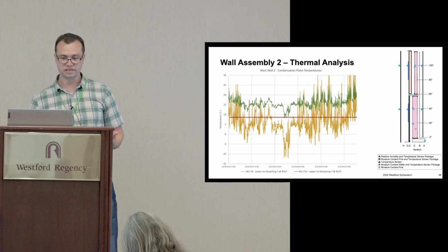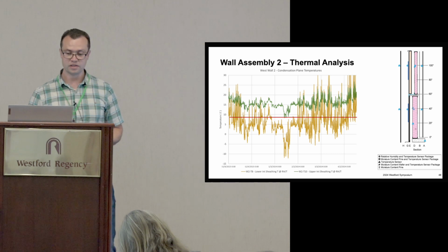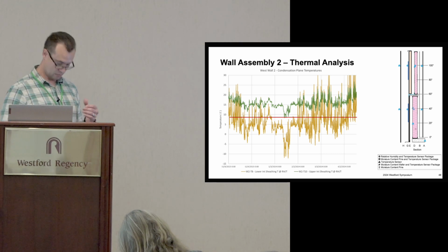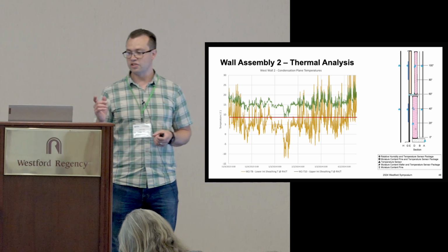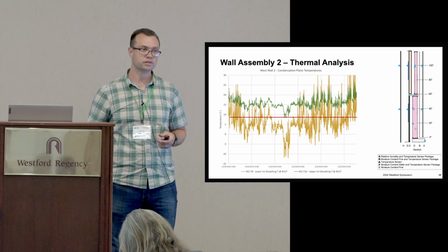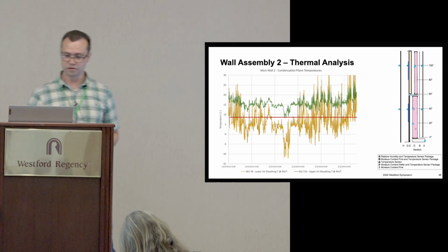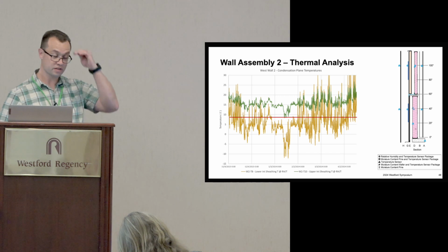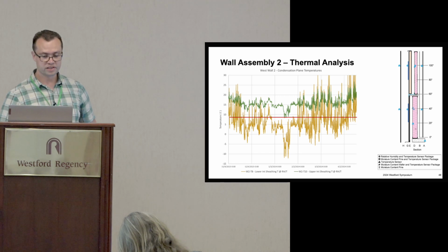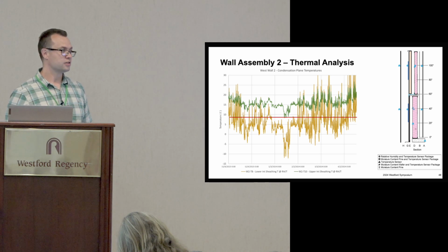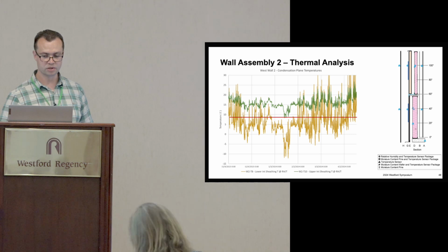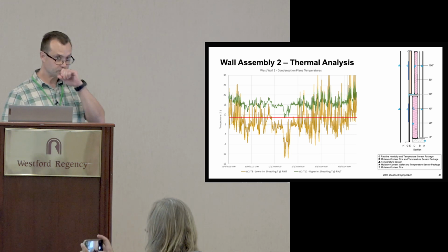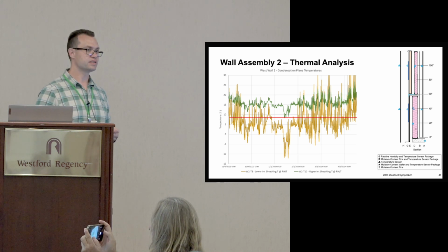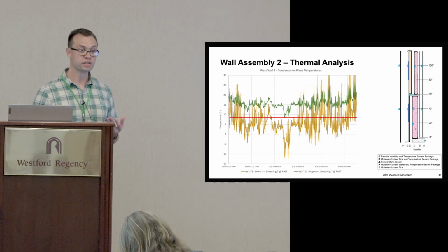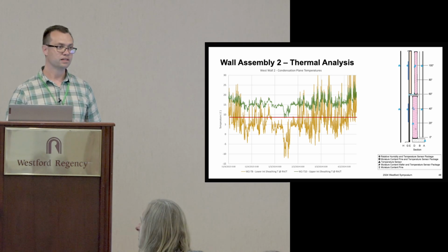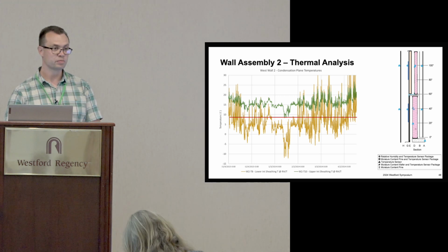What does it look like from a thermal analysis? So this is the air leakage condensation potential. So this winter, one of the other things that we can do is mess with the RH inside the test hut. And so for this winter, it was running at 72 and 40 RH. So that's something like an 8 or 9 degree dew point. So that's the red line. So the wall with exterior insulation is the green one up top. And the wall without exterior insulation is the lower line. This is hourly data. So between November and April, for every spike or duration that the orange line is below the green, that's an hour of possible air leakage condensation if and when we inject air. Because we do build these test walls pretty tight so that we can do this baselining to say what's the humidity, what's the temperature, and what's your risk profile.